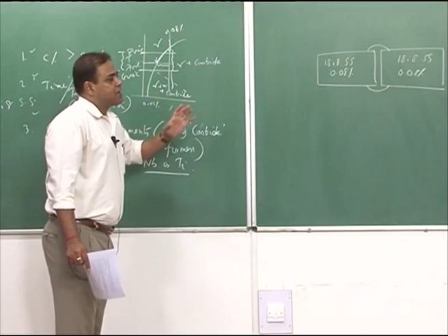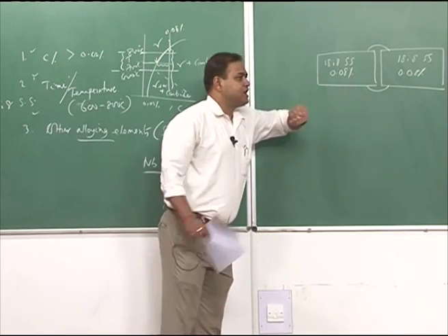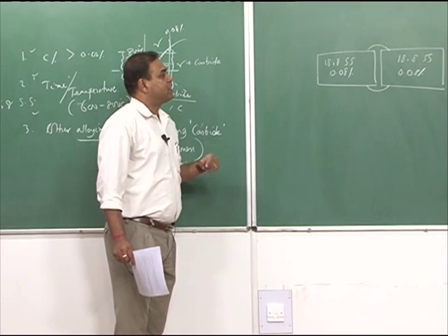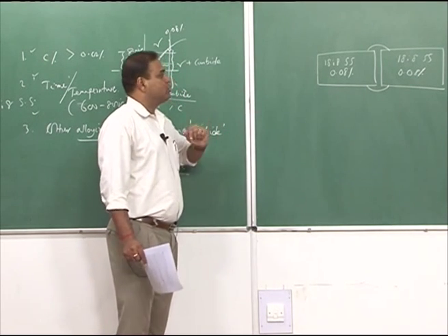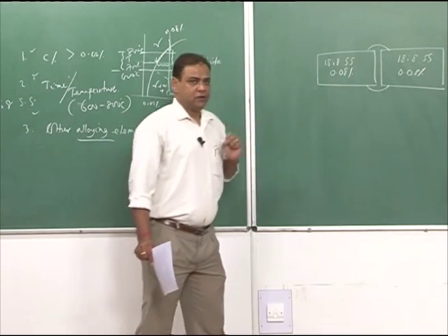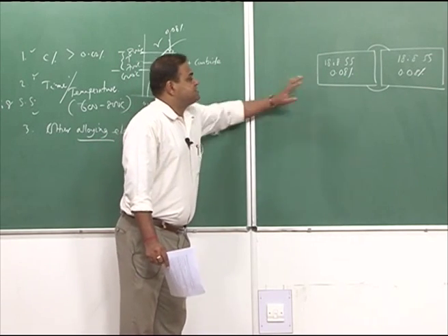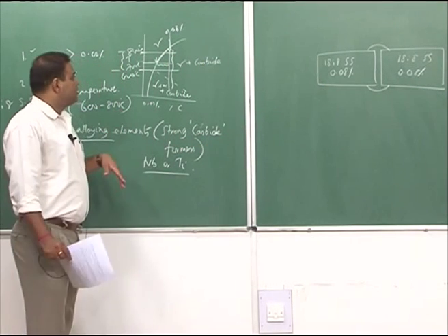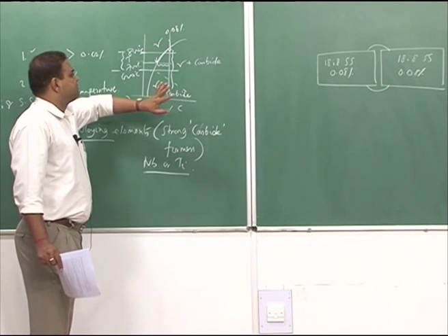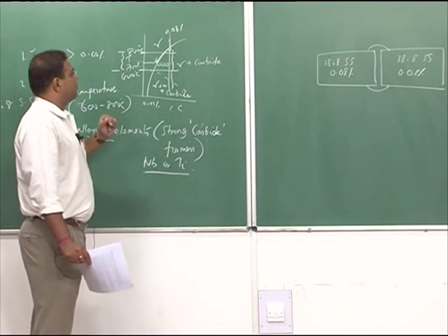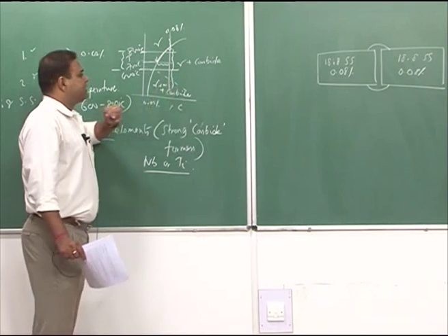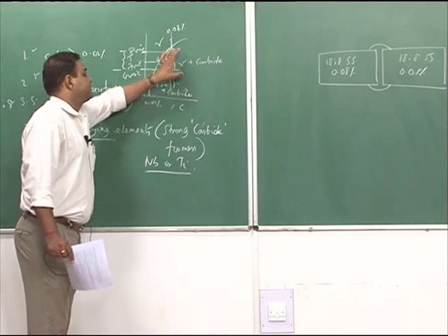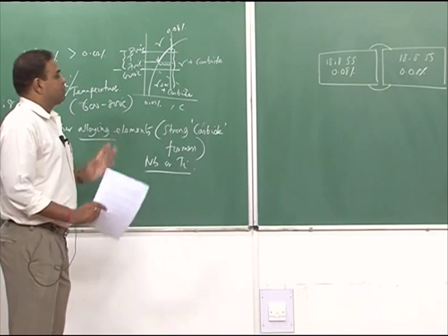So, individually these two blocks do not have the problem of intergranular corrosion, because chromium carbide has not formed along the grain boundary in either block, and the chromium always stays in solution. Let us say the heat treatment followed is such that chromium carbide precipitation does not occur. How can we go for that heat treatment? We can quench it rapidly, so that chromium carbide does not form in this temperature zone. Fine, we do not have any problem.